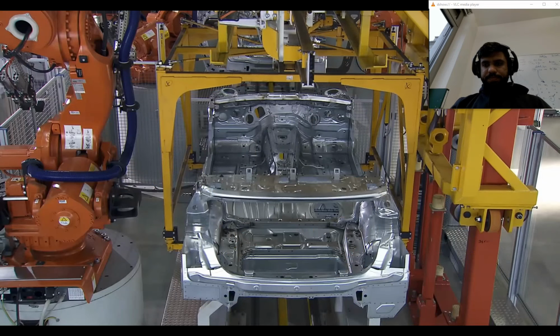Now, when we cut a sheet, it has different artifacts. You will see that the surfaces are not very straight here and here and here and here. As the shearing takes place between the two edges, there is a slight deformation lip here, and then there is a burr. We call it burr here, and they are important. We don't want these plastic deformations to be too large, and we don't want them to be too small. We want to keep our tolerances. If we want to cut a very small piece of 3 millimeters or 4 millimeters, we want to make sure that it is 3 millimeters or 4 millimeters, and therefore we want to make sure that the part is of desired size. We need to maintain this clearance.